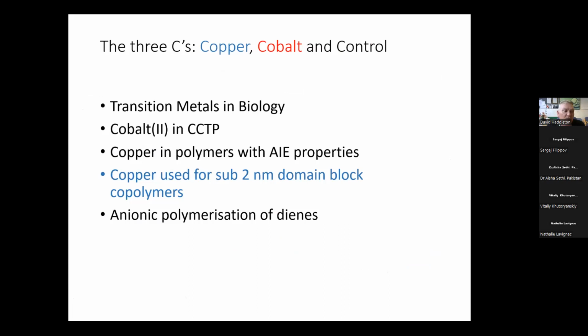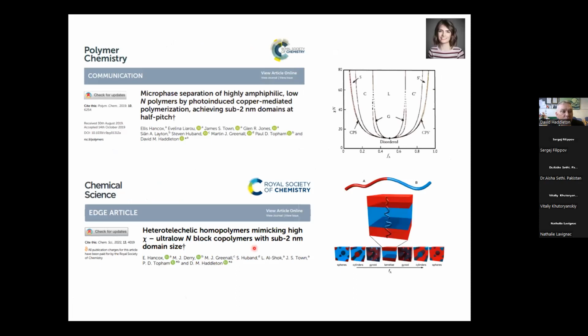Now, the second bit where we use copper is to make these very small domains. And this has been published in two papers, from this student who has finished now, Ellis, and we did this with Paul Topham at Aston, who's our SAXS expert. These are the world records. So these papers, which is sub 2 nanometers, this is the lowest nanometer domain size. And Paul Topham gets very frustrated because no one cites us because we're not really in the microphase separation club. But nevertheless, if you are in the microphase separation club, you might want to look at these papers.